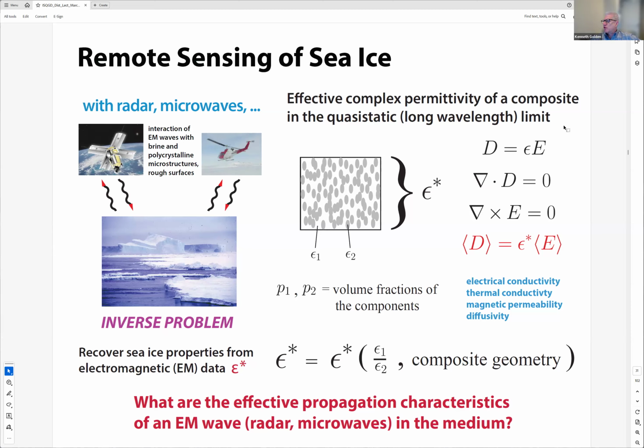These are the quasi-static Maxwell's equations. Here's the constitutive law, divergence-free, curl-free, and then this defines the macroscopic homogenized parameter, epsilon star, which of course is a tensor. And it's a complicated function of the ratio of the constituent parameters, the brine and the ice, and the composite geometry.